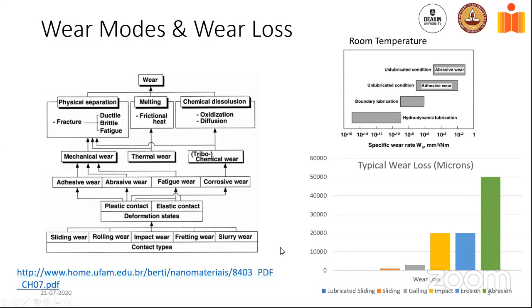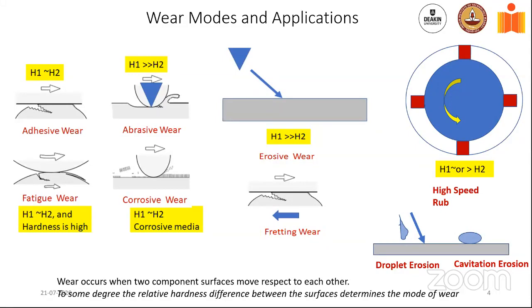So having said that, what are the different modes of wear? We would go to slide 4. It's a simple cartoon that tells you what are the different modes of wear. You have adhesive wear, typically takes place when the component hardness of the two surfaces are roughly the same. So that's H1 of surface number 1, H2 of surface number 2. Those are the hardness values. They're roughly the same. With the abrasive wear, one of the surfaces becomes much harder than the other. And quite often, it also happens because you have sharp particles thrown in, which is what you see here. Sharp angular particles, which are hard. Those are the ones that actually cause abrasion.